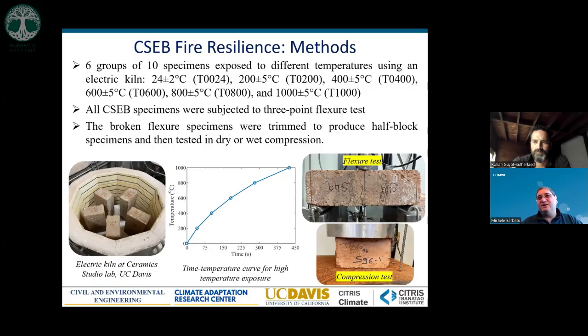And so after heating the materials for several hours, we tested them under a 3-point flexure test to find the modulus of rupture. And then the 2 parts of each of the specimens were trimmed to produce the specimens for compression tests that were tested both with dry compression and wet compression.